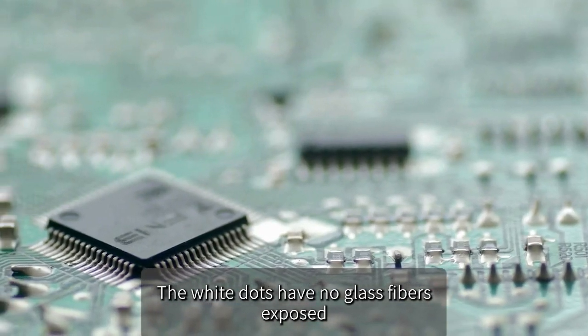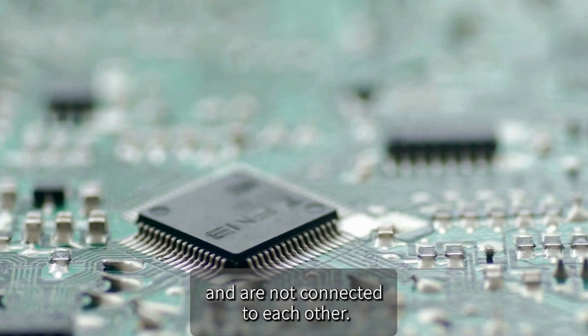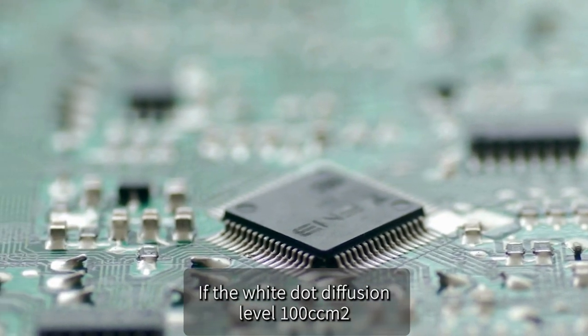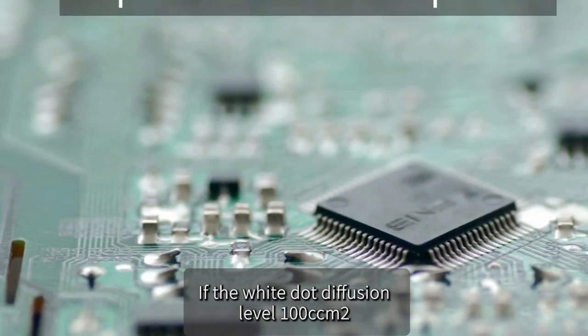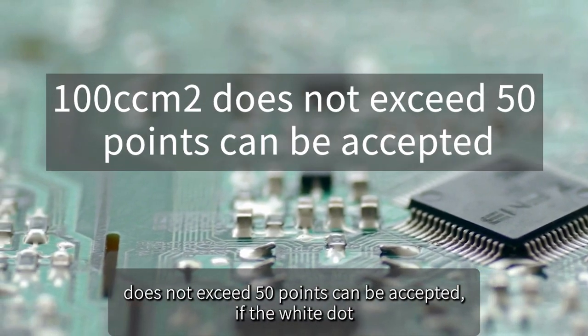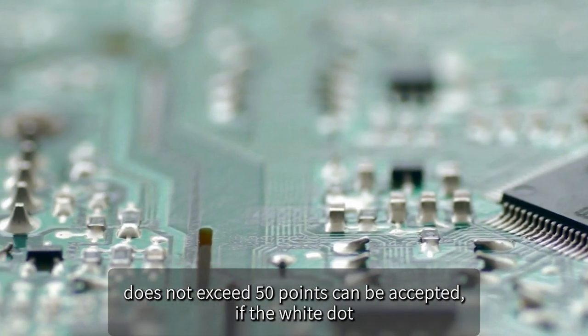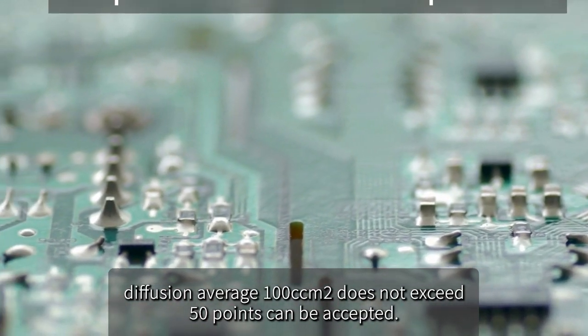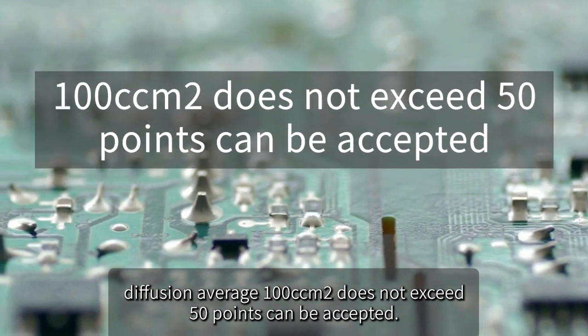Base copper. The white dots have no glass fibers exposed and are not connected to each other. If the white dot diffusion level 100 cm² does not exceed 50 points, it can be accepted. If the white dot diffusion average 100 cm² does not exceed 50 points, it can be accepted.